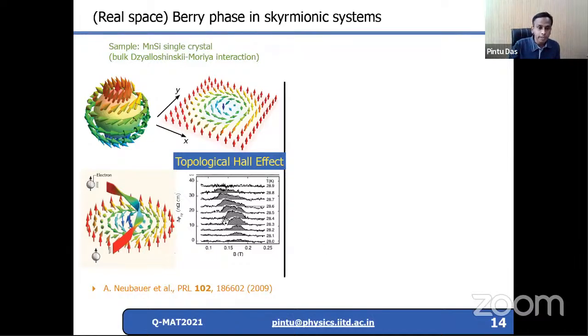So this is a typical Hall effect signal. In a typical Hall effect signal, what one observes is a topological Hall effect due to the skyrmion phase. The skyrmion introduces a real space Berry phase as the electron traverses a skyrmion, as you see here. So because of this real space Berry phase, you see a topological Hall effect,